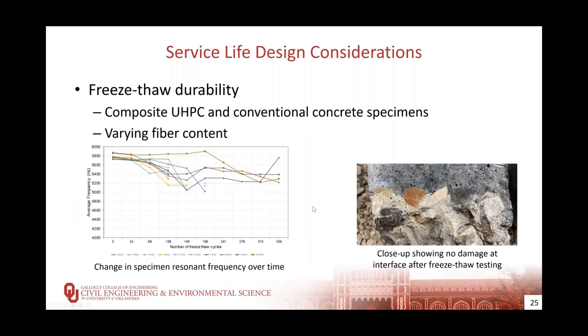Even for the 0% fiber specimens, the interface between the UHPC and conventional concrete did not exhibit separation or damage, as shown in the right side of the slide. And for all other fiber contents, the majority of the damage occurred in the conventional concrete.